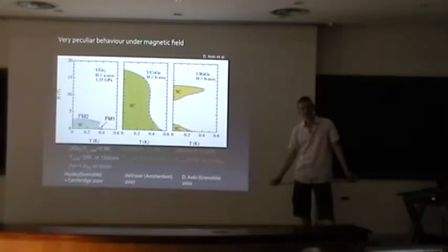And we actually looked at this recently in terms of the effect of superconductivity on certain phonon line widths, because if you have a phonon with a particular Q vector, it can connect Fermi surfaces at different distances, and in principle, you can pick out which Fermi surfaces you're probing, and it's a complementary probe to neutrons, which do something of the same. But I'm just saying, as a general problem for people to think about, I think it's very important, and where we should be heading with studying multigap systems.